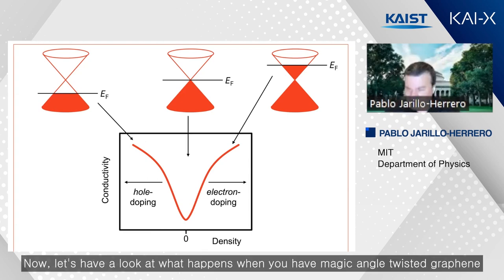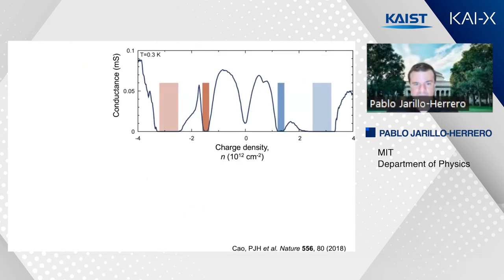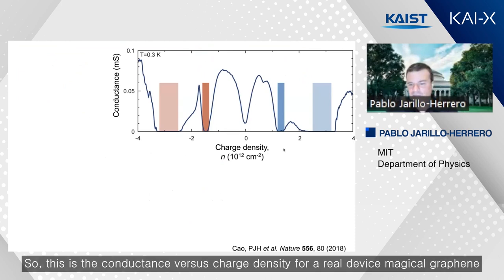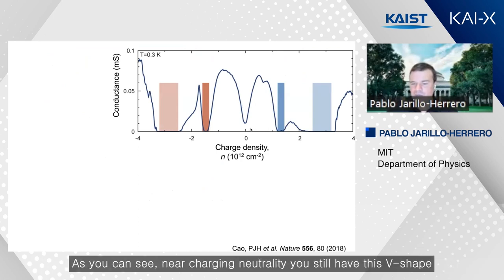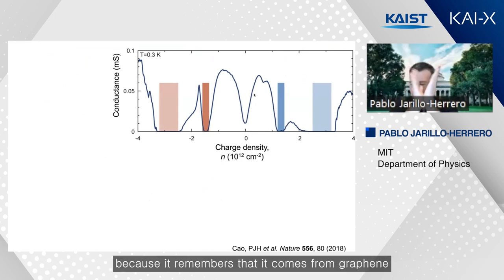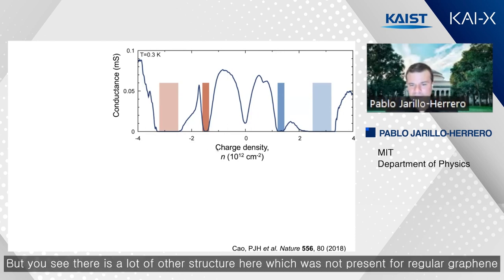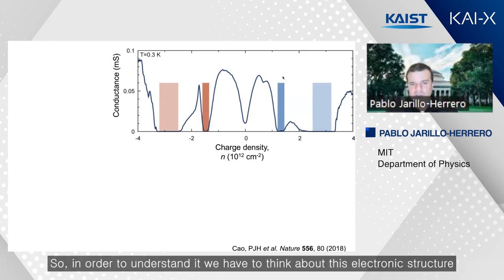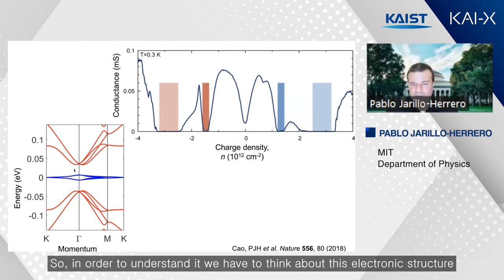Now let's have a look at what happens when you have magic angle twisted bilayer graphene. So this is the conductance versus charge density for a real device, magic angle graphene. As you can see, near charge neutrality, you still have this V shape because it remembers that it comes from graphene. But you see there is a lot of other structure here which was not present for regular graphene. So in order to understand it, we have to think about the electronic structure.